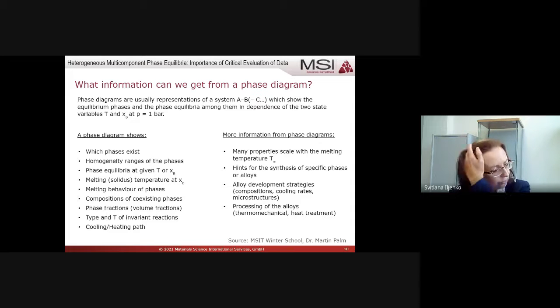What information can we get from the phase diagrams, just when we look at the phase diagram? So first, which phases exist? Homogeneity ranges of the phases, their extension, phase equilibria at a given temperature or composition. Also, melting temperature at a particular composition from the solidus. Melting behavior of phases, whether they melt congruently or incongruently, by which reaction. Compositions of coexisting phases. Phase fractions we can get from the phase diagram, type and temperature of invariant reactions, cooling and heating path.